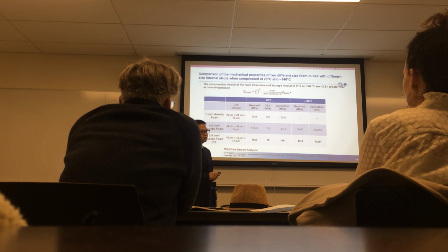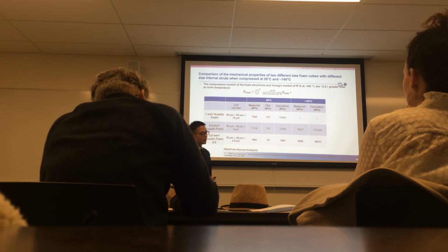At first, we use 3D design software to design the foam structures. Then we export a file. This file will be used in the 3D printer and can also be used in the simulation. So the physical sample has the same structure as the simulation structure. During the simulation, I follow the same process as the compression: apply the force on the top surface and record the displacement. And depending on the force and displacement, I calculate the elastic modulus of the foam structure.